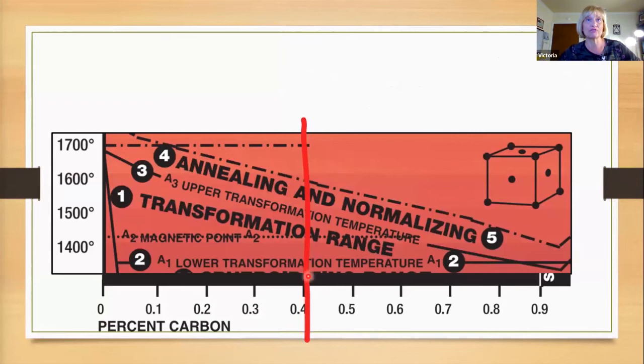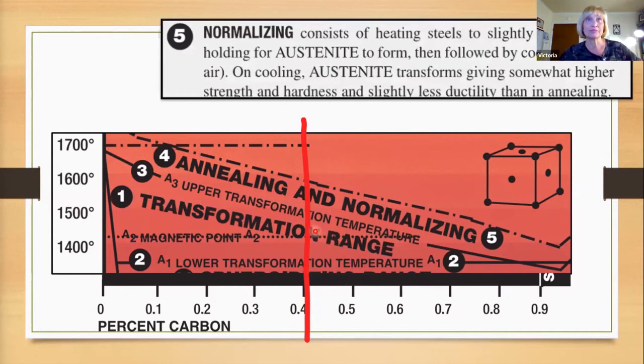I drew in our line for our 0.4% carbon. We have our lower transformation temperature here, which is just below the 1400, and along our percent carbon range, we get to our upper transformation temperature, which is on a slant at just above 1500. Right above that, when it's all austenite, that's what our normalizing is.